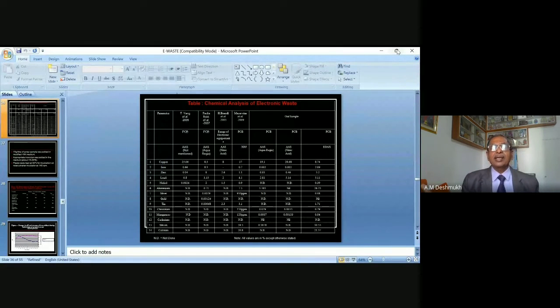There are many chemical analytical methods. So an atomic absorption spectrophotometer is required. And by various methods, we analyzed it and we found that yes, in our electronic waste powder, there are a number of metals. Which metals are there? Copper, iron, zinc, lead, nickel, aluminum, silver, gold, tin, chromium, manganese, cadmium, silicon, and calcium. Many other metals were also detected in the electronic waste.